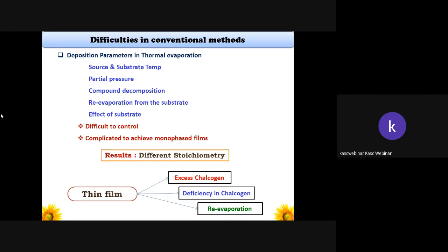So it's very difficult to control also by using the conventional method of preparation. And it's very, very complicated to achieve monophased or single crystalline thin films. But yet it results in a different stoichiometry. For example, if the material possesses a certain amount of a chalcogenide, then one can expect that there may be excess chalcogenide after preparation of a sample, or there may be a possible chance of a deficiency or lacking of chalcogenide in the material, and re-evaporation of a material from the surface of a sample.